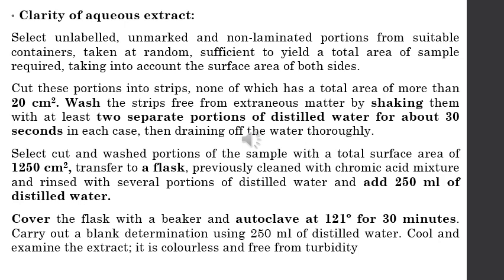In the first case, we cut the portion of the container into strips such that the total area, that is the area of both sides, is not more than 20 square centimeters. Wash the strips by shaking with at least two separate portions of distilled water for about 30 seconds, and in each case drain off the water thoroughly. So this is the first case.